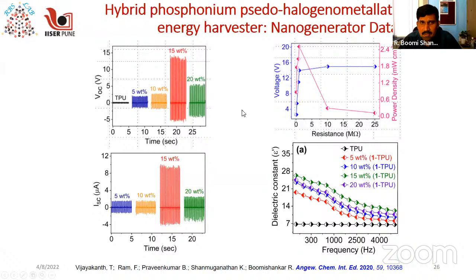As I told you, the performance of the material varies with the loading percentages. We see that the neat TPU polymer is actually non-dielectric. However, when you load it with the ferroelectric particles, the dielectric constant of the material increases, especially at lower frequencies, where the ferroelectric particles are more dominant than the bulk polymer. As you increase the loading, the dielectric constant increases up to 15 weight%, and when you go to 20 weight%, the dielectric constant decreases, which means that the dipole moment of the system is reduced beyond the threshold loading. This tells you that the best performance of the 15 weight% material comes from the highest dipole moment of the system.